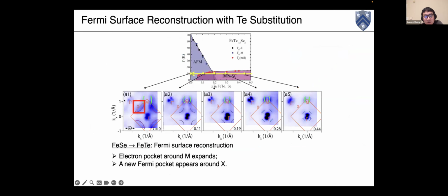Then let's take a look at the Fermi surface mappings. From the Fermi surface mapping, we find a very interesting Fermi surface reconstruction from the optimal doped compound to the iron tellurium end compound, which is that the XY hole band around the Brillouin zone center seems to gradually evolve to a Fermi pocket around the X point. This is very interesting, and we want to know the origin of this evolution.